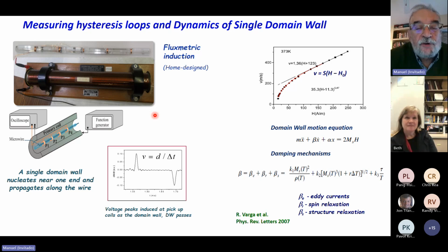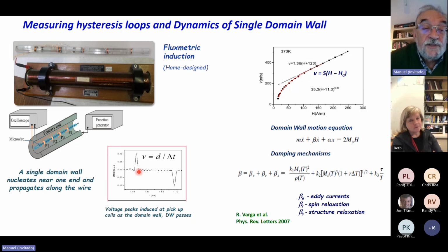So, just to tell you that to characterize these magnetic microwires, in principle, is not very difficult, apparently. So we applied an axial field with a solenoid. Then we have a number of pickup coils inside the solenoid, and inside the pickup coils, we have our microwire. So the velocity of propagation of the domain wall can be determined just from considering the distance between two pickup coils, which is like 1 centimeter, and the difference in time between the induced pickup signals, which is around 1 millisecond, so we can determine the velocity.